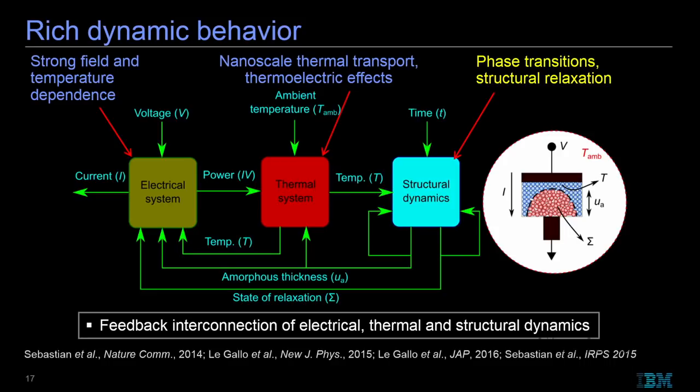In a sense, there are huge thermal gradients within the device, which means that thermoelectric effects will start playing a role. But of course, what is also very interesting is that it has very interesting structural dynamics, such as crystallization and structural relaxation. I will come back to it when I say how we can do computation using the structural dynamics, right? So that is why it's very interesting. We should be able to exploit the dynamics of PCM devices to perform computation in place.